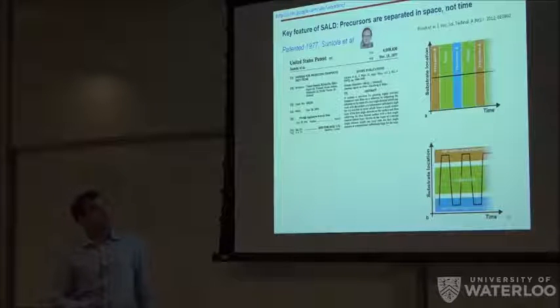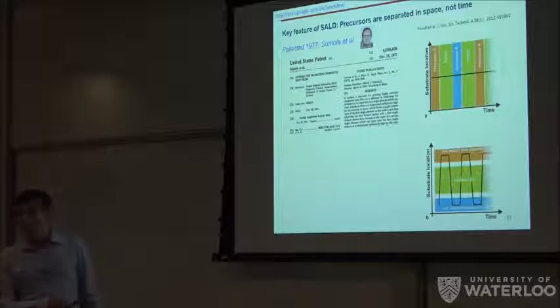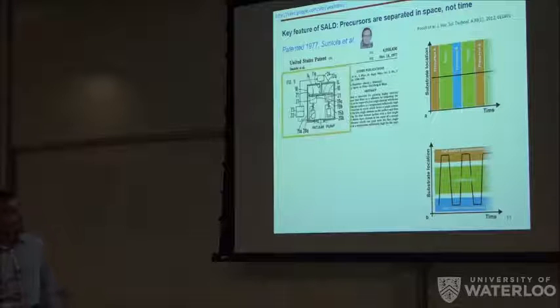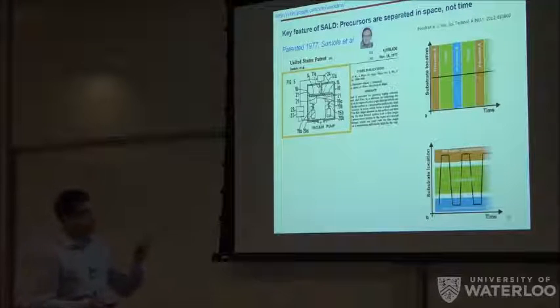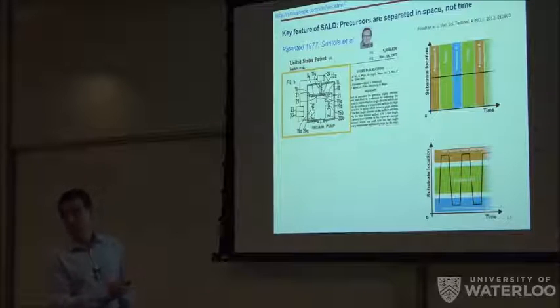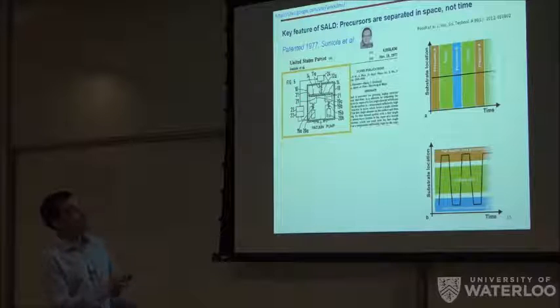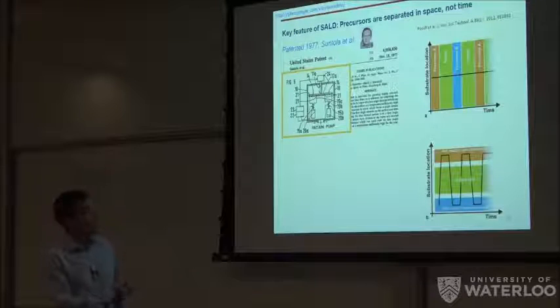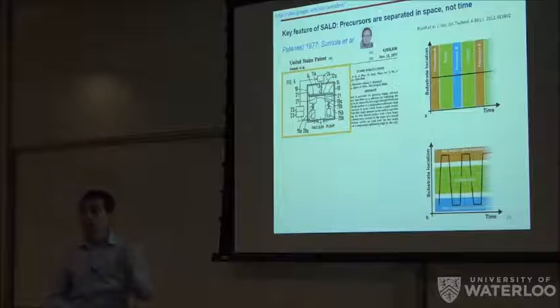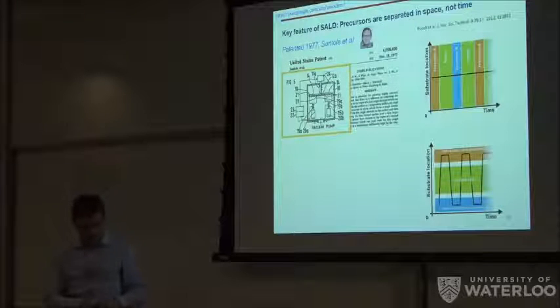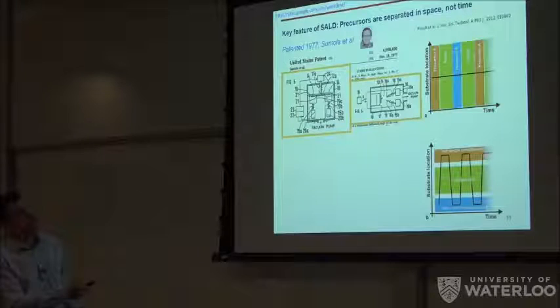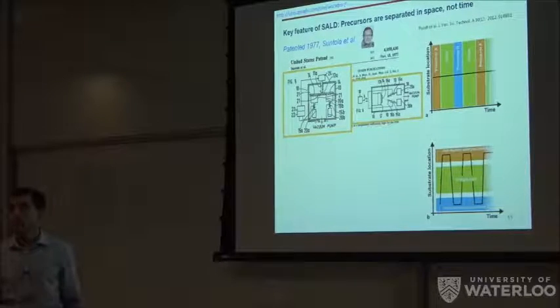And if you look at the figures and the reactors he proposed in his original ALD patent, you can see that the first three designs he proposes are the spatial ALD reactors, where you have two precursor bottles and you have a rotating substrate holder exposing the samples to the different precursors with a vacuum pump to eliminate any unreacted precursor. And then only the fourth design corresponds to a temporal reactor in which you sequentially inject the two different precursors.